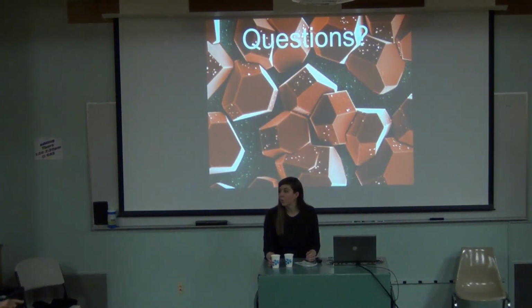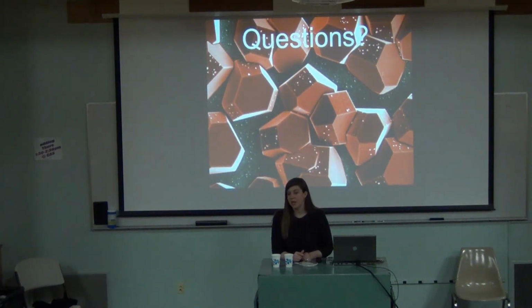One last question. I see that you've annealed with, what was it, argon? Mm-hmm. Did you just use the natural property of argon to create an annealing schedule? So the reason we were initially using argon is because it's supposed to be inert and not cause any changes. We didn't see that was the case with the manganese system, but we did see that was the case with the iron. It didn't seem to do anything. People have also annealed with other things. So you can anneal with hydrogen sulfide and sulfur dope, or you can anneal in the presence of ammonia and nitrogen dope. So you could anneal with lots of different things, but we were picking argon to try to keep the oxygen content the same and to keep everything the same.